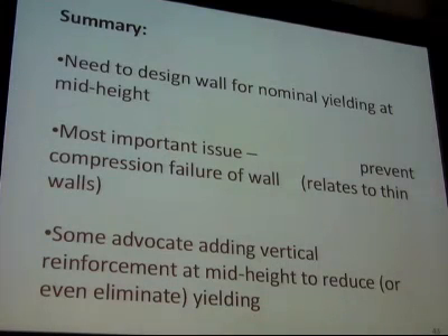Okay, so the summary from that is that, in my opinion, we don't need to provide special detailing at the mid-height of the shear wall. And in fact, we haven't added that. We do need to be careful primarily about these compression failures. And this relates to what I talked about earlier, that we don't want to have large compression strains in the wall. Okay, and some people advocate the idea of actually preventing the yielding, and I'm actually against that. I think a little bit of yielding at mid-height, at small curvatures, is a good thing because it helps reduce the shear demands.